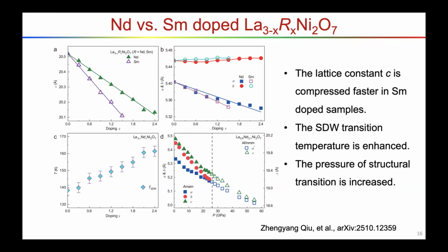Yeah, I fully agree with you. The magnetic structure is very complex in the nickelates. There are some neutron diffraction measurements proposing different moment sets on different nickel sites. I didn't mention that work in this talk. But that could be happening here also, right? Yes. In calculations that we've done on different kinds of magnetic order, one does indeed find very strong changes in the amplitudes of the spin, but also in the way that they order.